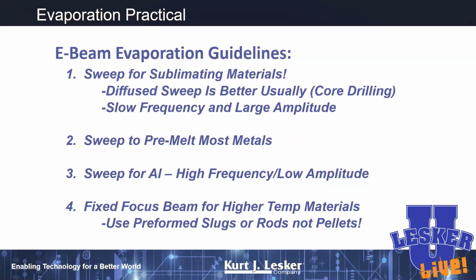But again, I do want you to pre-melt those metals. And so if you start out with pellets, I would prefer that you pre-melt those things into one solid chunk before you actually do your deposition. Generally speaking, you would like the surface of the material that you're depositing to be pretty flat. If you've got big peaks and valleys there and you're sweeping the beam around, you're going to be changing the shape of your flux pretty frequently.